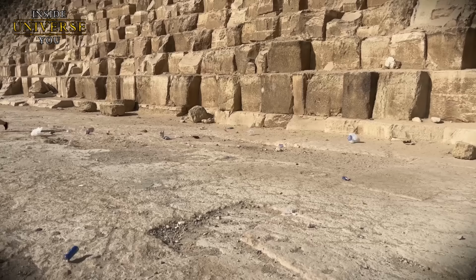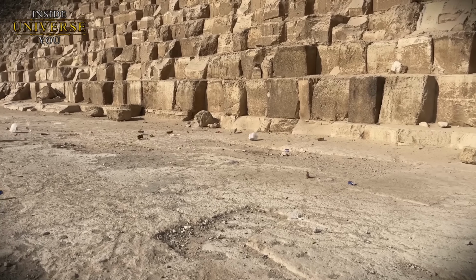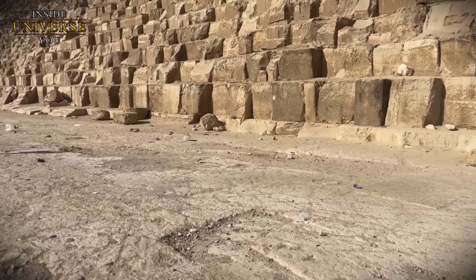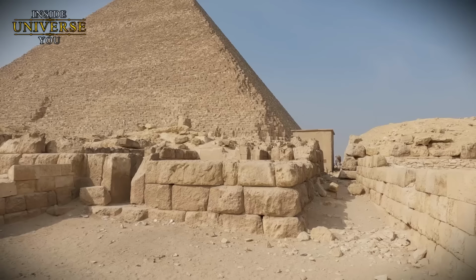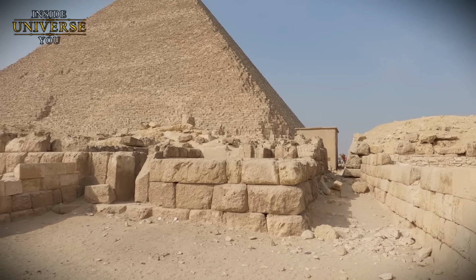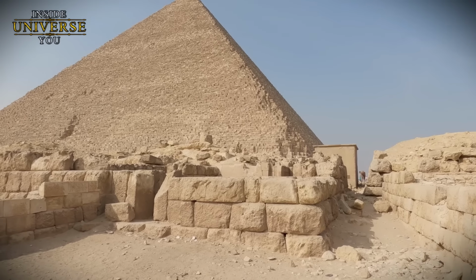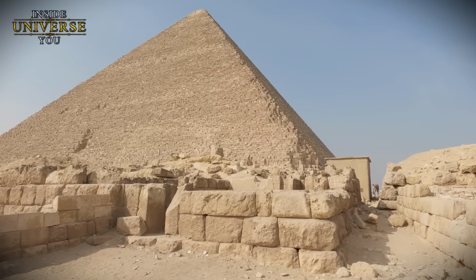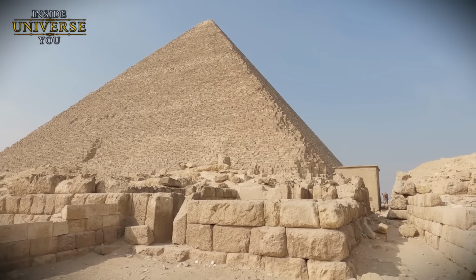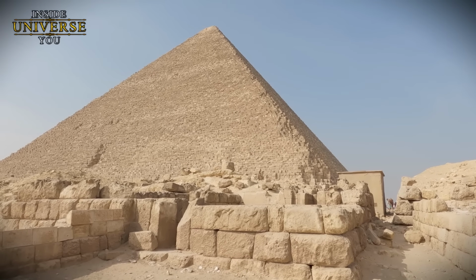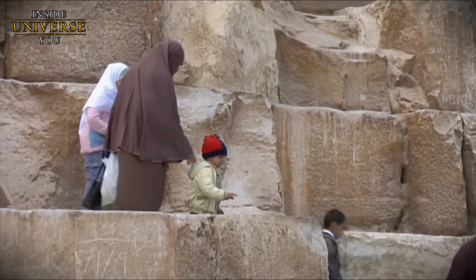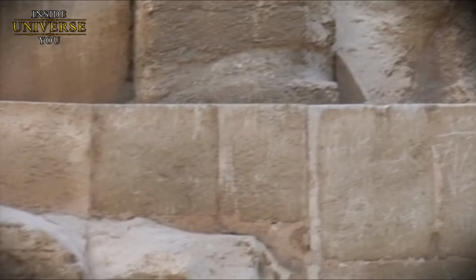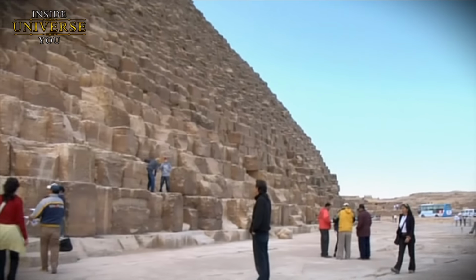One of the biggest gaps in the geopolymer theory is that the majority of pyramid blocks closely match the natural limestone of the Giza Plateau in composition, texture, and fossil structure. Many geologists who have examined large numbers of blocks report that their mineralogy, grain boundaries, and sedimentary features are consistent with quarried stone, meaning a small fraction of the blocks could be cast geopolymer.